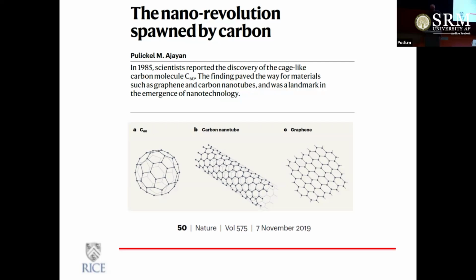You can, in fact, peel off from graphite very thin layers of graphene. They stack up to make graphite, so easily peelable. And that's how the Scotch tape method ended up discovering the graphene material. But again, this whole story has something to tell, because intuitively, one would have imagined that graphene would be the first thing to be discovered because it was already there, right? But the whole thing started with fullerenes, which is probably the most complex of these three structures. And then came the carbon nanotube and then graphene.